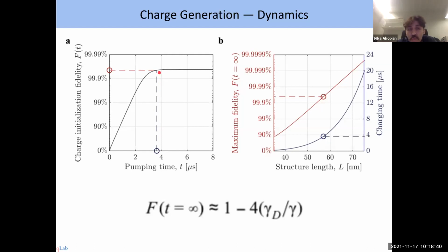create electron hole pair. Now we can also increase fidelities if we want of our charge initialization simply by increasing the length of our structure. Why is that? Because when we increase the length of our structure, the wave functions of electron and hole are more confined, and the overlap is smaller. And the smaller the overlap, the less unwanted recombination. So by increasing the structure, we decrease the overlap and increase our fidelities.